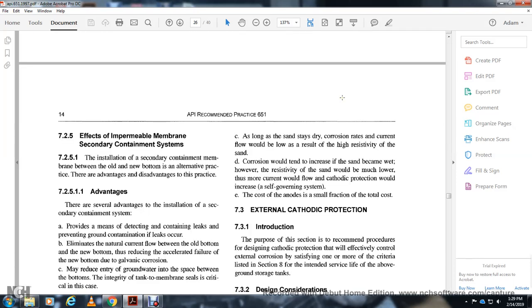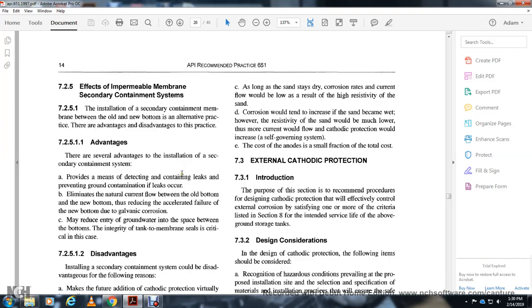Alright, 725, the impermeable membrane with the secondary containment system. The installation of the secondary containment membrane between the old and new bottom has advantages and disadvantages. There are several advantages to installing a secondary containment system: it provides a means of detecting leaks, prevents ground contamination if there is a leak, eliminates natural current flow from the old bottom to the new bottom, reducing accelerated failure of the new bottom due to galvanic corrosion, and reduces the entry of ground water into the space between the bottoms. The integrity of the tank membrane seal is critical in this case.